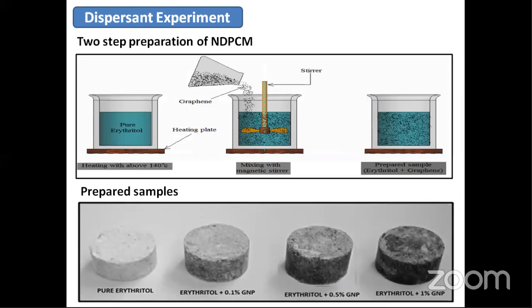Then dispersion experiment. Graphene dispersed erythritol PCM was prepared by a two-step method. The erythritol was melted at approximately 120 degrees Celsius on a hot plate and then poured into a beaker. The beaker was kept in an ultrasonic vibrator for 2 hours. A certain amount of GNP, that's graphene nanoparticle, 0.1%, 0.5%, and 1%, was added to the molten PCM.